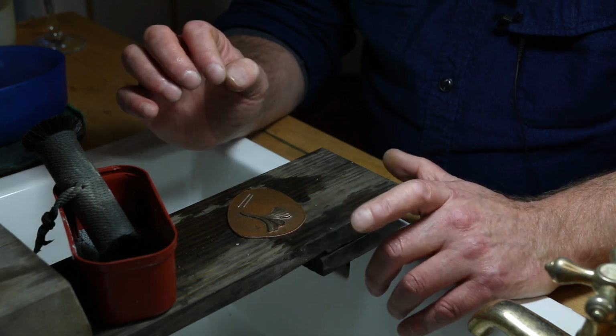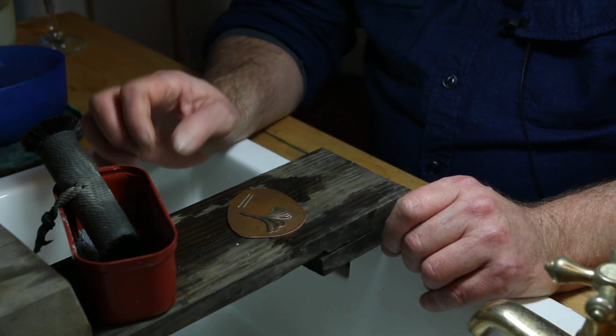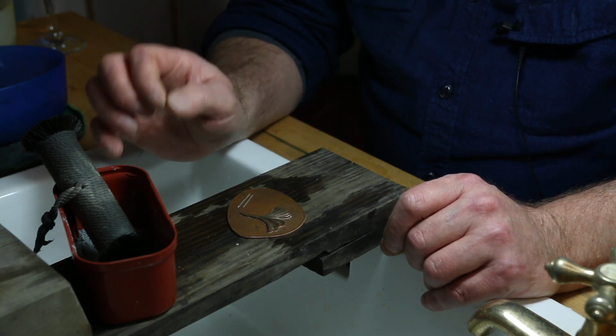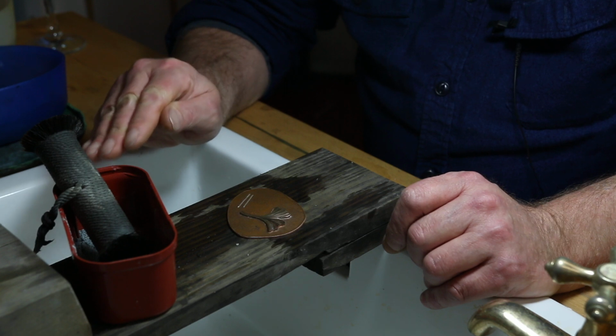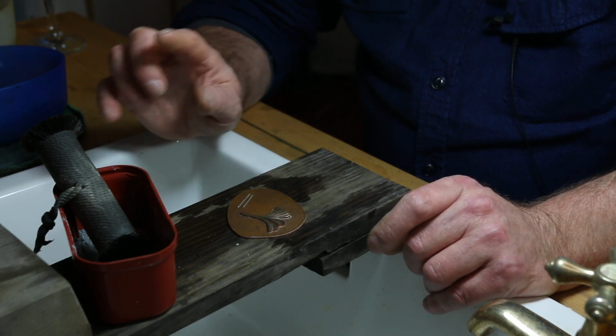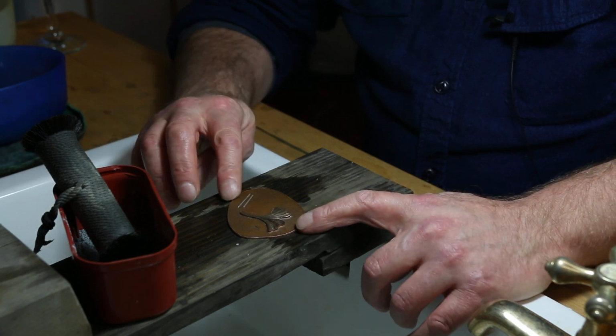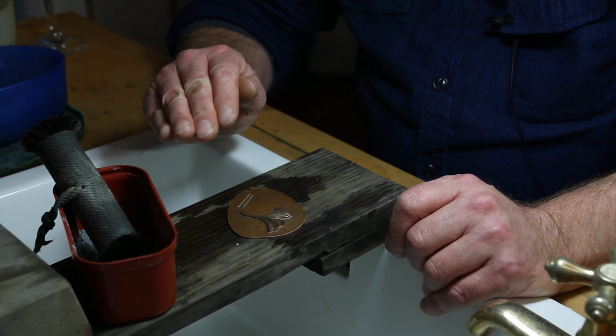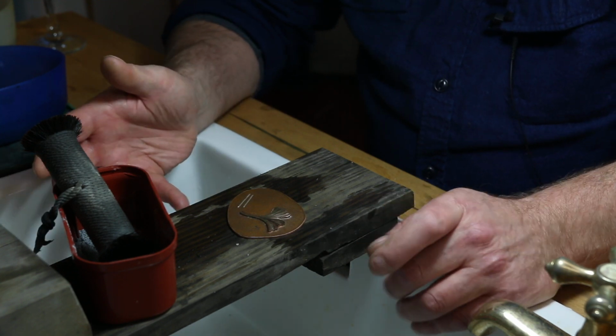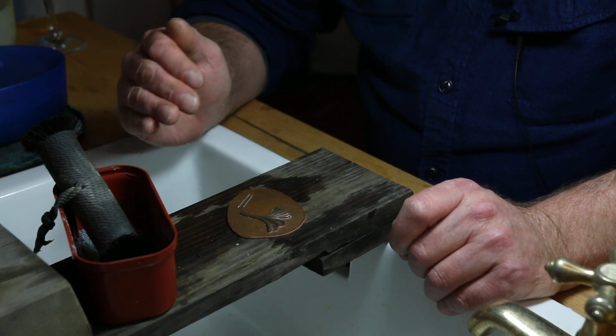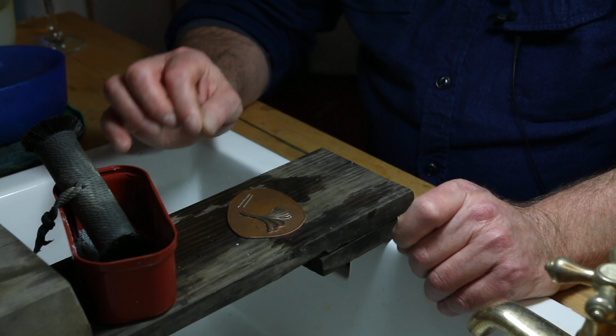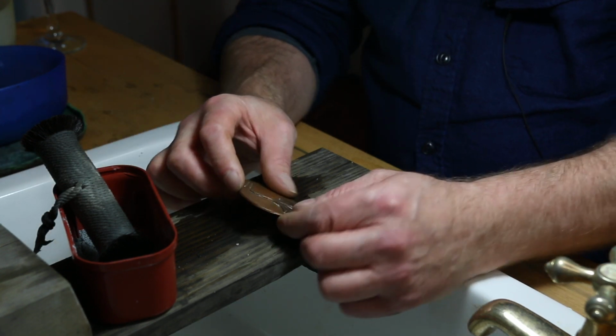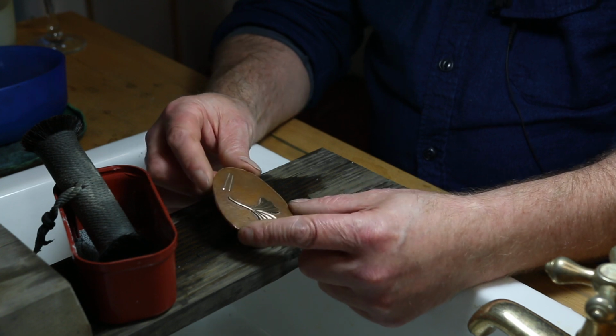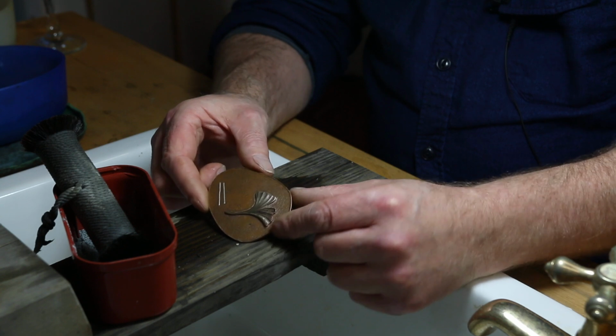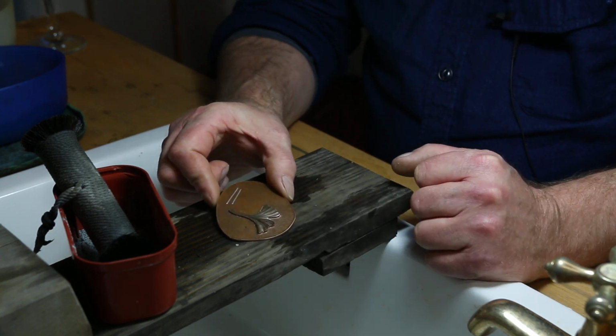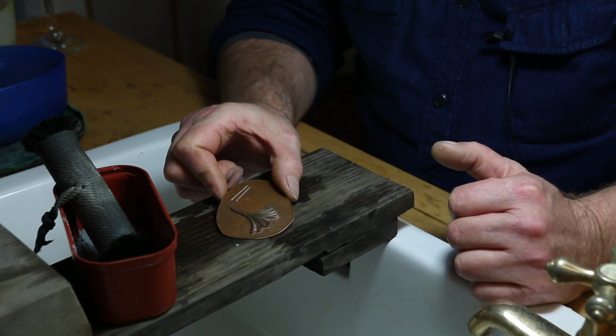It's really crucial that the surface of the metal that goes into the patinating solution be completely fresh. By this I mean that an outer layer of molecules of metal and metal oxide has been completely stripped. It's for this reason I invariably will clean it as well as I can, patinate it until a color starts to develop, which will also then reveal any stains, any streaks or anything like that, and then I will go back and polish it once more. The second time always yields a better result. I think we'll proceed now with the polishing, and as we go along, I'll talk about any minor details. That way I'm not overwhelming you with too much all at once.